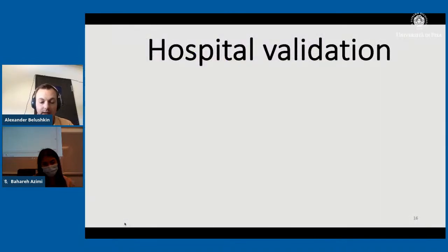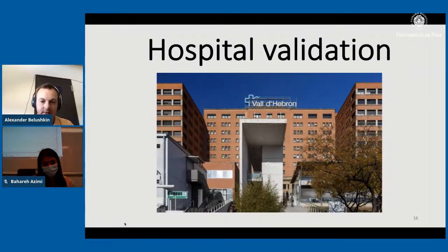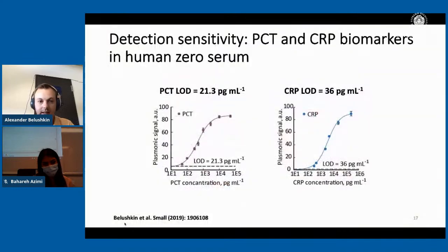So having that on hand, we packed all our stuff and embarked on a trip to Barcelona from Switzerland, not so far away, but still you have to take all the stuff to test with the real samples. Before doing the actual patient sample testing, we had to determine the sensitivity limit and the dynamic range for both PCT and CRP. As you can see here, we have pretty similar performance. For PCT, we have about 21 picograms per milliliter limit of detection and about 3 orders of magnitude dynamic range. And for the LOD of CRP, it's about 36 picograms and a very similar dynamic range.